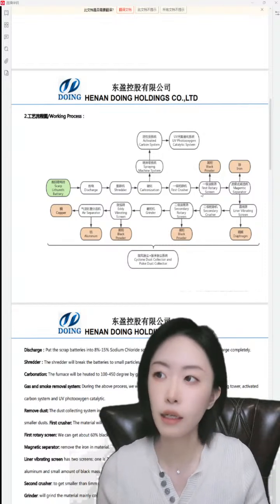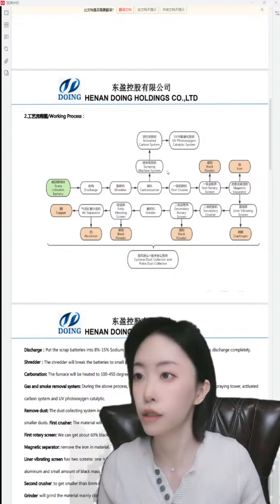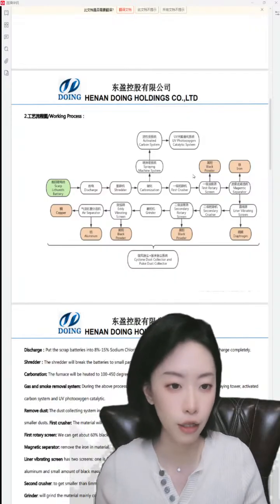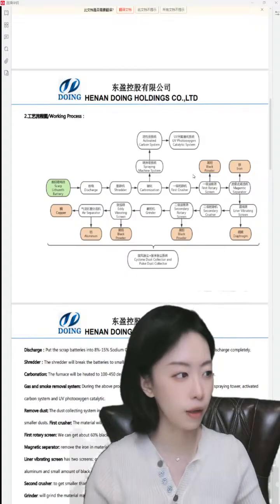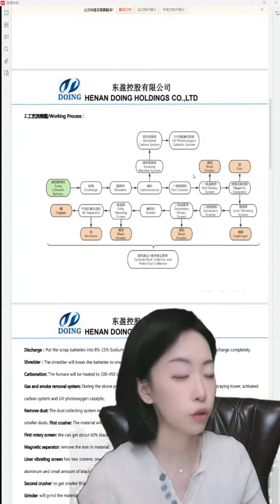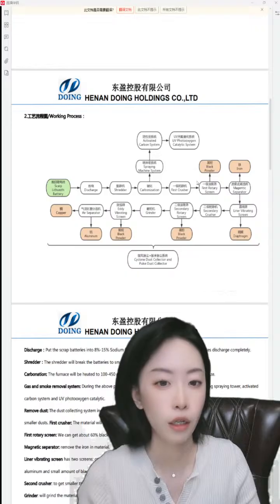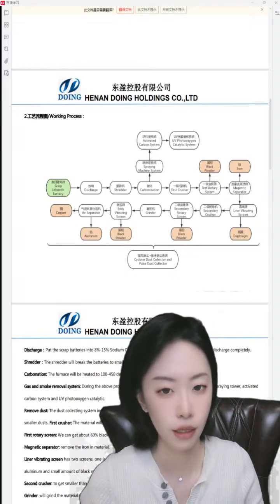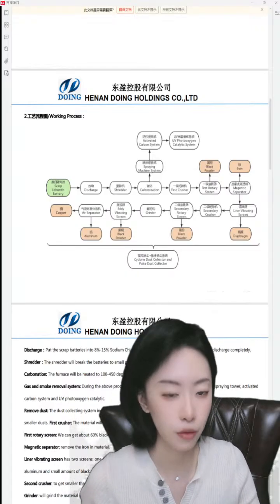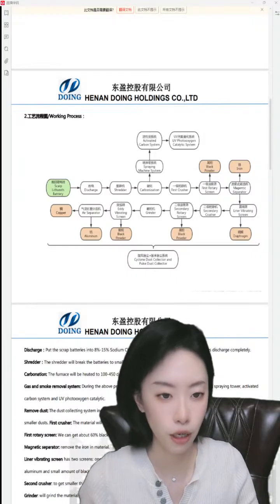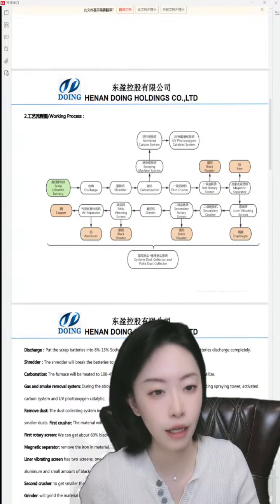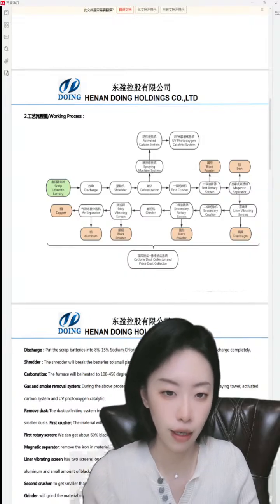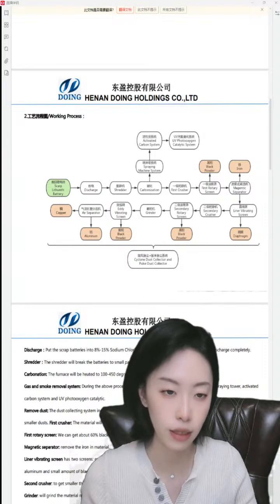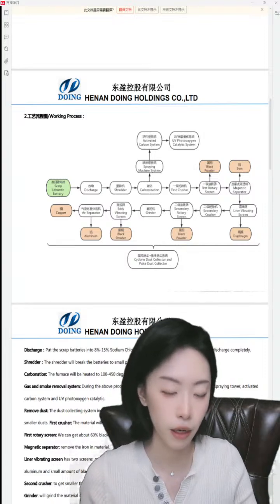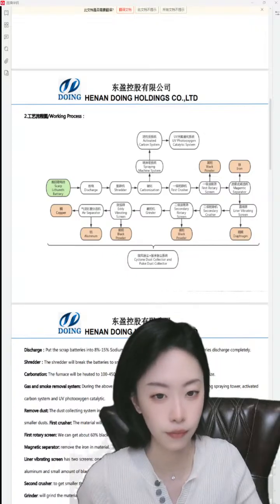Okay, and then after processing, we will use this first crusher to crush the particles from 2 to 3 or 2 to 5 centimeter to less than 10 millimeter. And the first one is the hammer blade crusher. It's a kind of impact crusher by the high-speed rotation of the hammer blades in the crushing chamber, so as to make the materials to be crushed and then get the particles less than 10 millimeter.